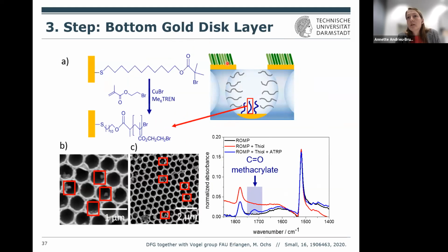Now you change the wettability, you change the solvent to ethanol, and this then again wets the pore, and you again use thiol chemistry to functionalize the gold, first with an ATRP initiator and then performing the ATRP polymerization. And then as well, you see that you get these kind of polymer blobs under vacuum in the electron microscope. You see, though it's small, you see the methacrylate band evolving in the IR spectra, which all indicates that there is a functionalization.